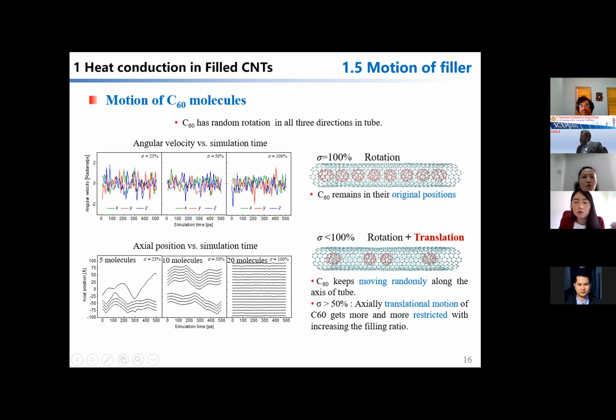random rotation in all three directions, no matter what the filling ratio is. The motion of each carbon-60 molecule is recorded in this picture. In a fully filled tube, in this picture and this picture, we can see that carbon-60 molecules remain in their original position. However, once not fully filled, carbon-60 could have translational movement along the axis of the tube. As the filling ratio is larger than 50%, interestingly, the translational motion of carbon-60 molecules gets more and more restricted with increasing filling ratio.